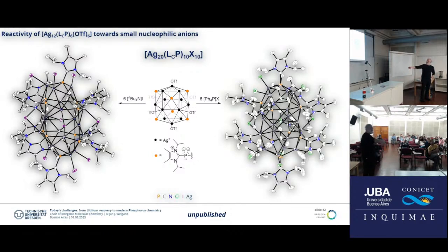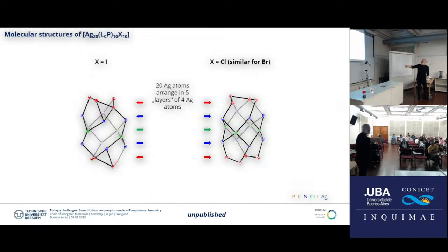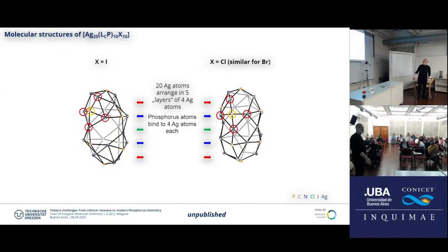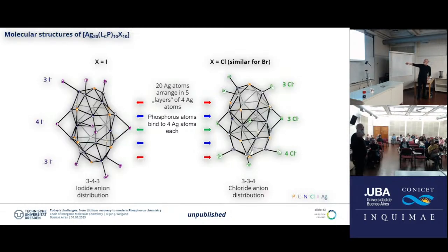Now, why is that interesting? Because that is something which we may know from the photo process, to make photos, to make silver nanoparticles. And these are now silver halogenides, and really growing an interconversion of those halogenides, which explains much more even our old photograph process. For the younger generation, which use a digital phone, it's not important anymore. The older version, which I consider myself being, and I used to work in a laboratory to develop old pictures. So this is for me actually very funny, that we really look into the formation of nano silver clusters. And we can learn about the different alternation and coordination, and then there's like 3-4-3 versus 3-3-4. So it's just a difference where the halogenides actually saturate.